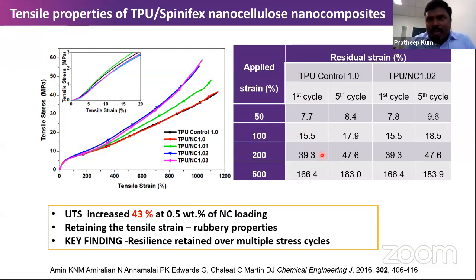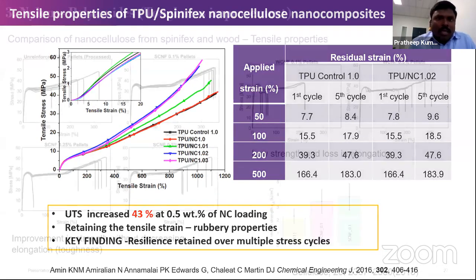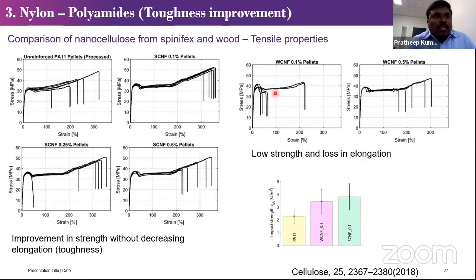So you can see that when we have the thermoplastic control, it's almost close. We are getting the resilient properties with the 0.5% nanocellulose. The other example material is a nylon-based material. So when we added Spinifex nanocellulose here in the nylon, which is polyamide-based, you can see this is the control one, okay? When you add nanocellulose, you can increase the yield strength and also the ultimate strength, without decreasing its elongation, okay? So this is the elongation.